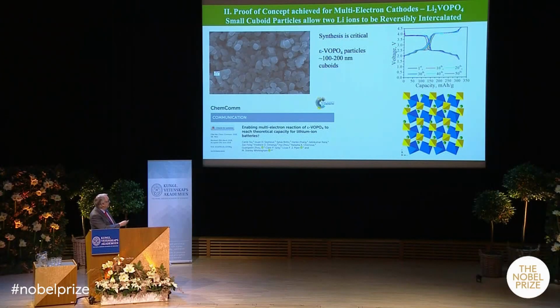And this is then cycling curves again. 1 plateau up here and 1 down here. And this is 50 cycles. And in fact, this material behaves better on the 50th cycle than on the first one. So we had proof of concept that we could, in fact, put 2 lithium ions into a crystalline lattice and intercalate in there without destroying that lattice. And that was critical. So now we can move on and see if we can do even better.